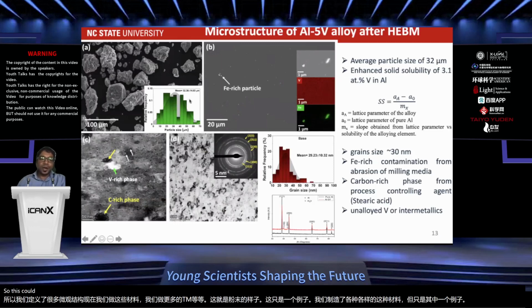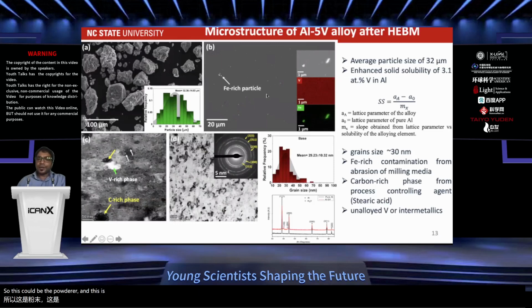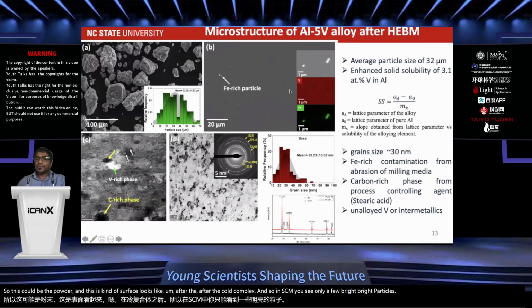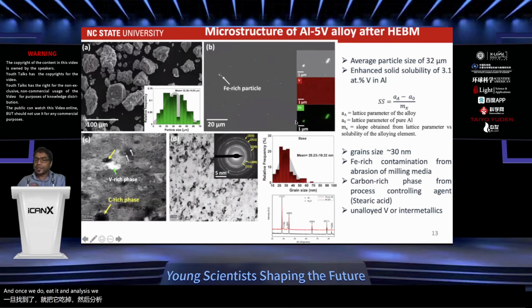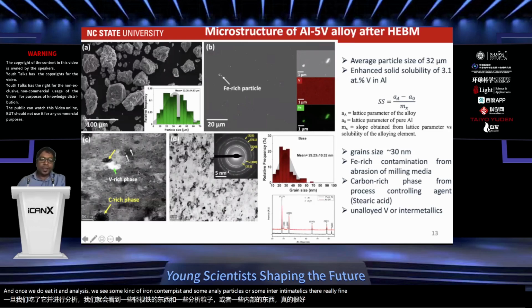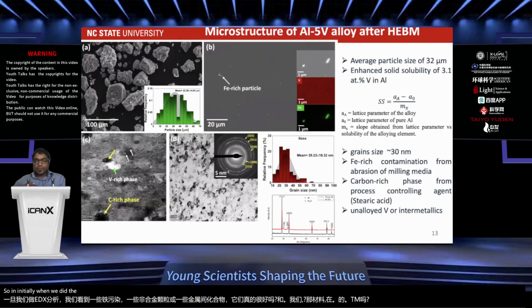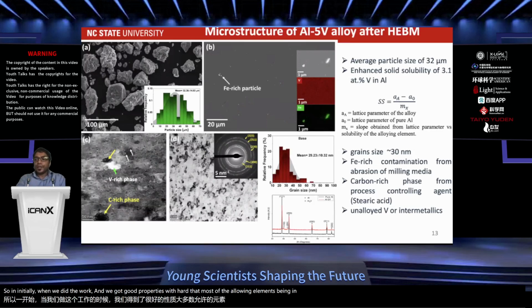So this could be the powder, and this is what the surface looks like after cold compaction. In SEM, you see only a few bright particles. Once we do EDX analysis, we see some iron contamination, some unalloyed particles or some intermetallics there, really fine. And we take that material into the TEM. Initially, when we did the work and got good properties, we thought that most of the alloying elements had been in the solid solution.